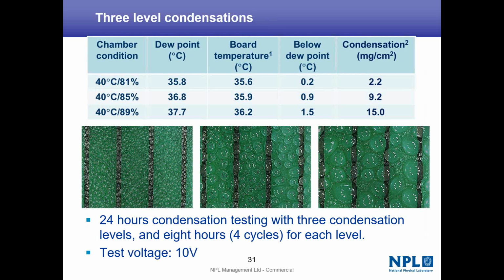What we've been able to do is condense known amounts or known volumes or known thicknesses on a surface. And this is basically by controlling the temperature in the chamber and the temperature of the subject, so to allow the material to condense onto the surface. So these are just some of the results. It gives you test chamber conditions, dew point, and a visual interpretation of the amount of condensation present on the board at these different set points.